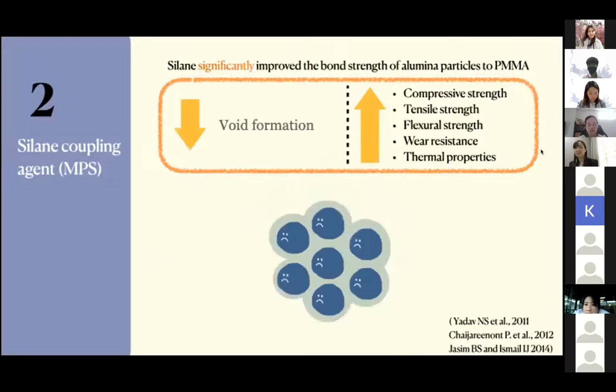Silane significantly improves the bond strength of alumina particles to PMMA by decreasing the void formation and increasing the compressive strength, tensile strength, flexural strength, wear resistance, and thermal properties.